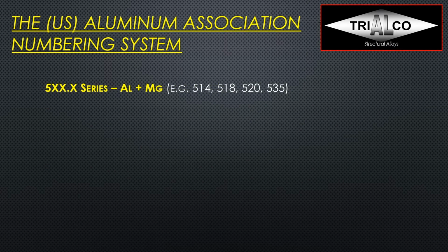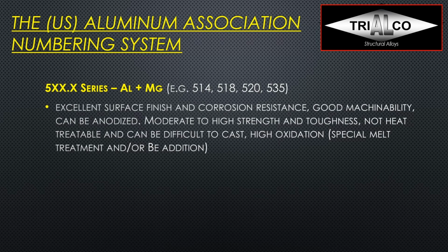And then we get to the 500 series alloys, and they are aluminum and magnesium. Pretty much nothing else in there. It shouldn't be. Typical representatives are the 514 or 518, the 520, and the 535, also known as Almag 35. They all have excellent surface finish and corrosion resistance. That's why they are usually used. Good machinability, and they can be anodized, and that's the special thing. So if you're looking for an alloy that can be anodized, that would